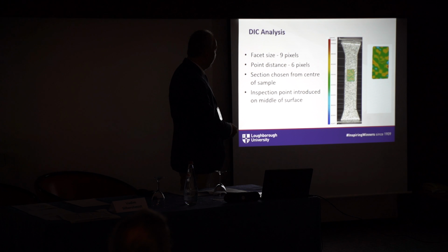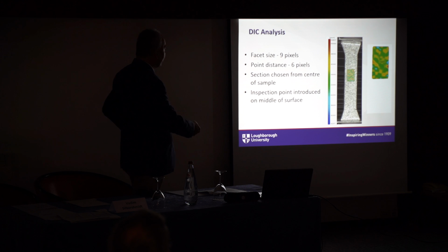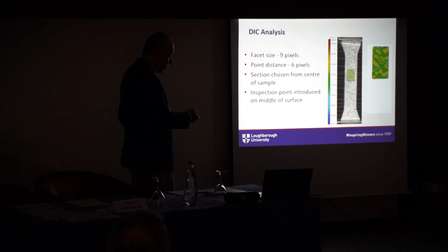So now you see that this is the window which is focused here, and this is what is happening clearly, because you have the kinematics of the movement of the specimen, so that's why it was going up. But you can see that we can have a reasonably good resolution of the deformation fields here. It is not seriously non-uniform, but there is still some non-uniformity related to the differences in the local mechanical properties.